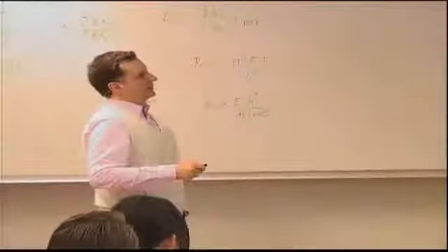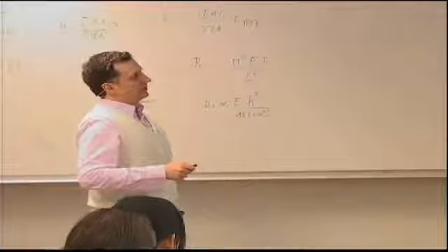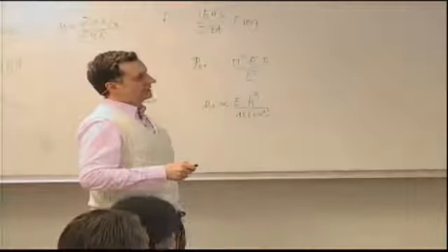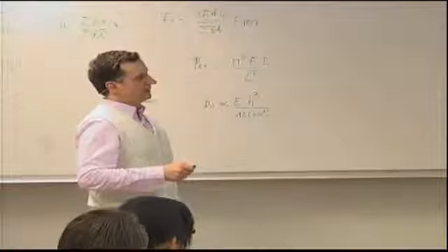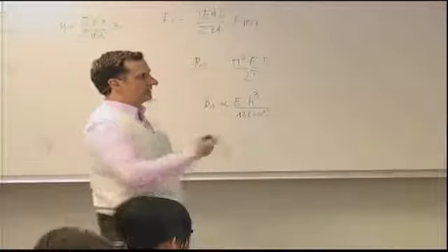So in principle, we recovered what we already knew, that the buckling load is given by pi squared over S squared times D11. N is set equal to 1 because that's the lowest buckling load. And if I divide that by thickness, I make it into stress. So this becomes my inter-rivet buckling stress, which is given by this quantity, pi squared D11 over t S squared. Now that's the case of a simply supported structure.